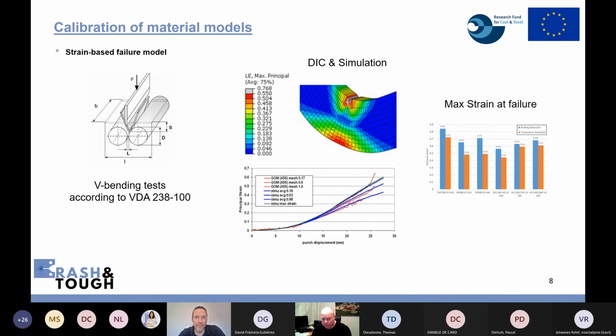As our colleague Pascal explained in the previous presentation, we also have a methodology to define the maximum strain at failure in bending condition, where we have a strong gradient of strain along the thickness, when we pass from compression to tension between the upper and bottom sheet surface. By the bending test following the VDA standard, with direct DIC correlation, and also using the simulation, we obtain the maximum strain at failure on the traction surface, of course. And we have all this information to apply in the crashworthiness simulations. And now we come back to my colleague Jorgen.